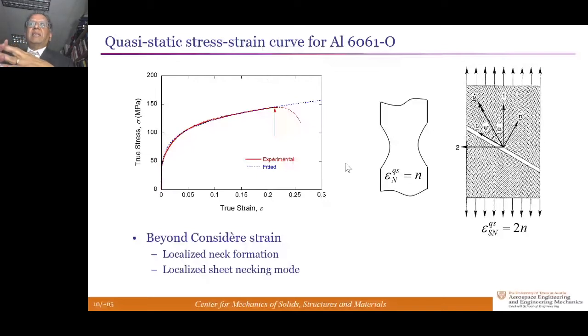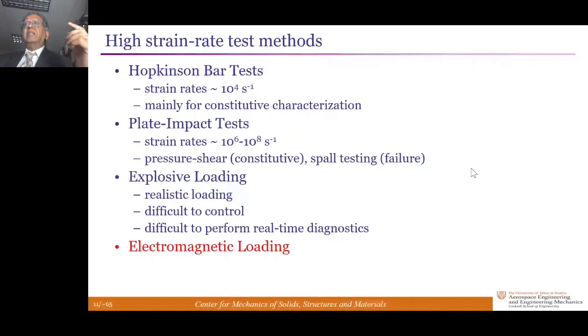There are a number of standard techniques for doing these kinds of experiments, and I won't go through the list of them. I want to highlight the electromagnetic loading because to me, it represents clean loading. It is a loading that arises without wave propagation. It loads through body forces, and the controls are done through electric currents. So the speed with which these things go is orders of magnitude larger than elastic wave propagation. So we decouple elastic and plastic wave propagation from the loading applied on the object.